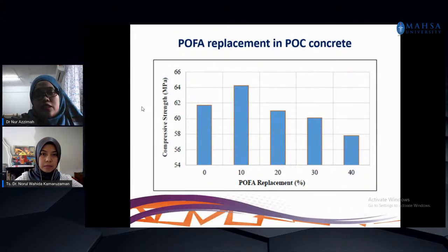So these are the results that we managed to get from the palm oil clinker research. It's a little bit different from the results for the oil palm shell. We can see that the compressive strength is much higher. Just now it was 30 something, but the palm oil clinker is a high strength concrete, around 60 megapascal. We target a strength of 60 megapascal, which is suitable for the construction of flyovers, bridges and high-rise buildings.